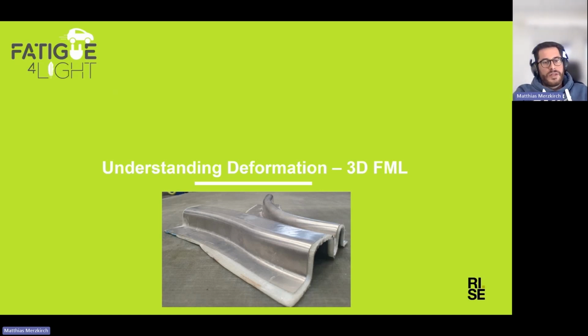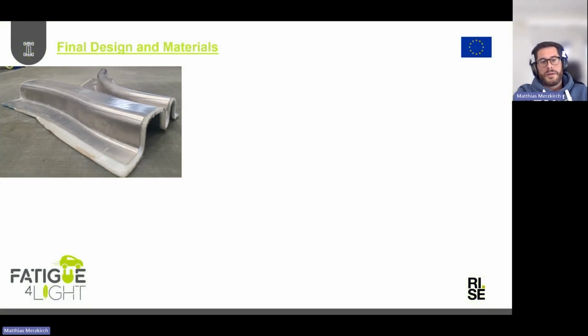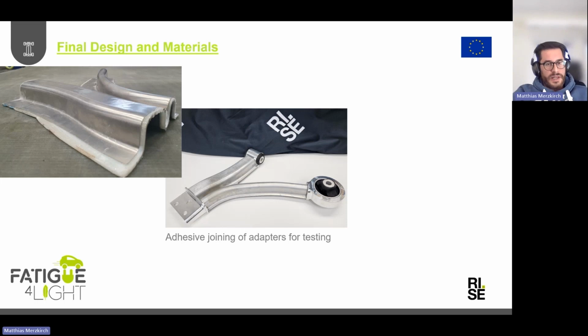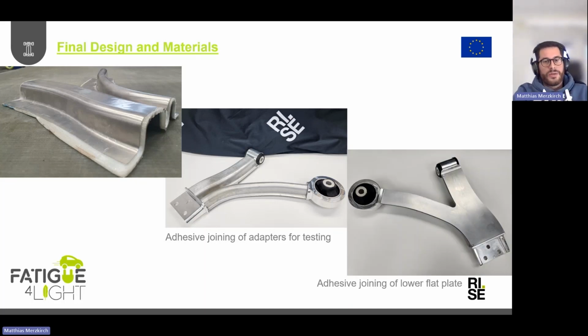And now this is the outcome. So that's what you see in this YouTube video, which is coming out of the press, and some makeup here and there is needed, especially for testing, which means removing the resin and the fibers outside there, and adding the adapters for testing, because at some point we want to do some structural testing here. And for that, the aluminum adapters were used, and also to incorporate the bushings as needed. So it sounds very comparable to what Michele showed earlier. And that joining has been done using adhesive, not only to incorporate those adapters, but also a plate underneath to increase the stiffness.